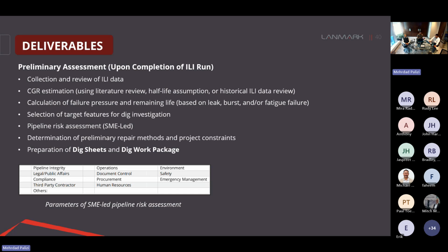Then we're going to have calculation for the failure pressure and remaining life. For different features, the remaining life is for different types of failures. It might be because of leak or burst in the case of corrosion, or in the case of cracks and dents, it might be because of fatigue failure. So some of the features that we do assessment over, they're going to be in a critical situation. So then we're going to have those features targeted for doing dig investigation.